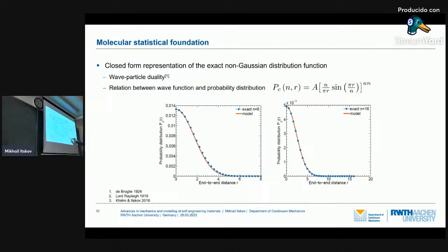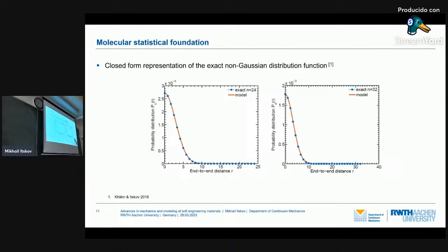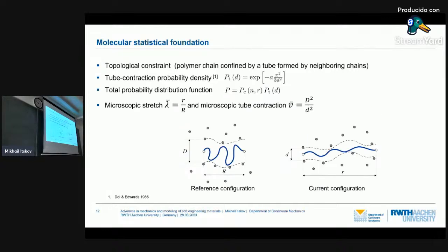You see this agreement is rather good for a short number of chains. This is number of chain 8, here 16. I don't know whether you can see it here or not because the quality is not quite good. And here for longer chains, 24, 32, and also you see with increasing end-to-end distance, this probability tends to 0, which is clear because if you try to extend this chain to the straight state, the probability is very, very low, almost 0, because the energy needed to reach the state is almost infinite, right? That is why it is described in this way.